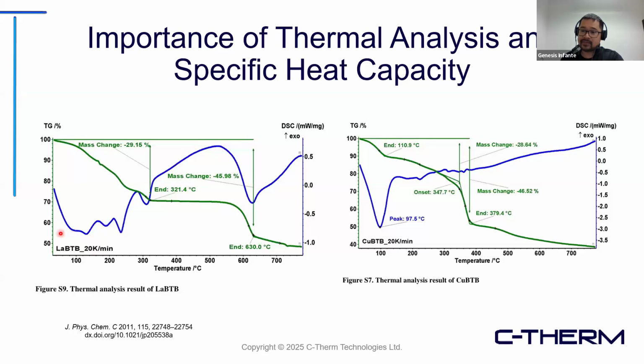And it's kind of a mess because it's very hard to really understand what exactly is going on here. But essentially, any peak occurring right here is an associated thermal event. In this case, you can see it's specified as exo in that direction, so they're all endothermic if we assume that the baseline is right here. During that mass loss, there are multiple endothermic events occurring. Then there's one major one, and then there's nothing for a while, and then another major thermal event, which is associated with the onset of degradation of the MOF. You can see a similar trend right here: some endothermic event, then nothing for a while, and then continuous degradation.